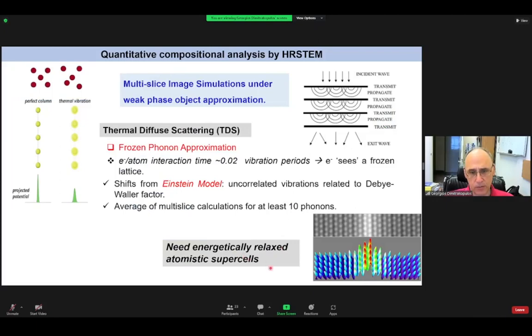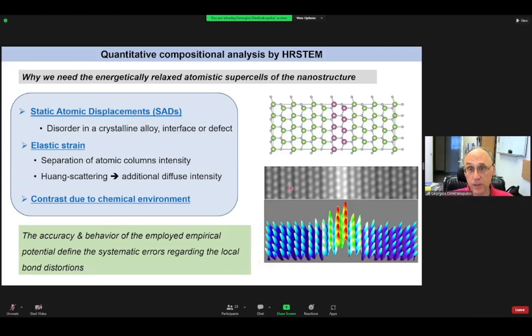Of course, in order to do this, you need to have, again, the energetically relaxed atomistic supercells, because these supercells, like this one, will give you what is known as the static atomic displacements because of the strain, because of defects, interfaces. Atoms may deviate from their normal positions. Also, the strain deviates the atoms from their normal positions. So it separates the atomic columns and changes their intensity. And also the chemical environment changes the intensity of the atomic columns. So you need to have the appropriate empirical potential, for example, if you are using molecular dynamics, in order to have an accurate model. If your structural model is not accurate, then your quantification will not be accurate.